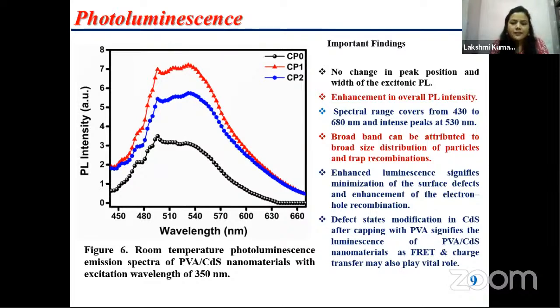And the enhanced luminescence signifies minimization of surface defects and enhancement of electron hole recombination. After capping, defect states are almost modified, which signifies there is tunability in their luminescence. The enhancement in PL intensity may be due to energy and charge transfer, which may play a vital role in this nanomaterial, which we will study in our further study.